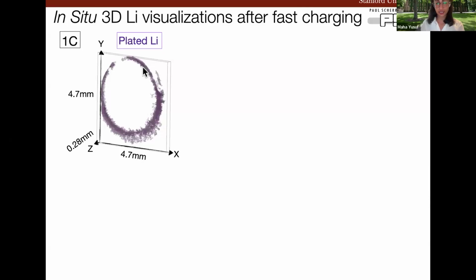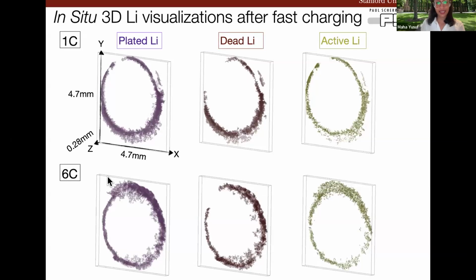The third example I will provide of in situ diagnostics is that of detecting lithium after fast charging and in its different morphological states. This experiment was done during my PhD at Stanford at the Paul Scherrer Institute in Switzerland. So here you can see 3D visualization of plated lithium at 1C, which is a relatively low charging rate. And the visualizations here are at 6C, which is a very fast charging rate, or about 10 minutes of charging.